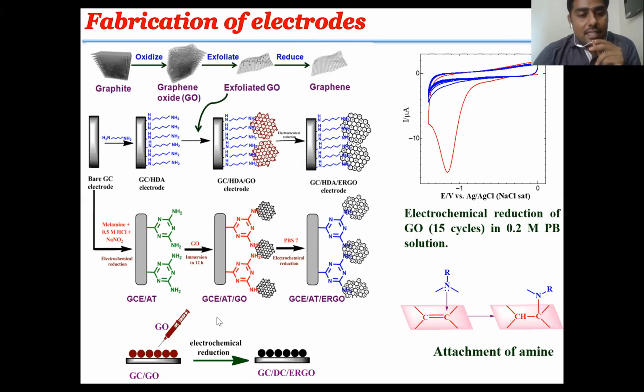So we have also another strategy, grafting. We have to first fabricate the amine-rich organic linker or heteroatom linker, and after grafting the amino compound, say a triazine ring, the graphene oxide is fabricated on the terminal of the amine functional triazine ring, and then it undergoes electrochemical reduction. Another strategy is drop casting of graphene oxide on the electrode surface. Of course, we cannot control the thickness and size of the fabricated material in the case of drop casting. And in the case of self-assembly, we can control the thickness of the graphene sheets.